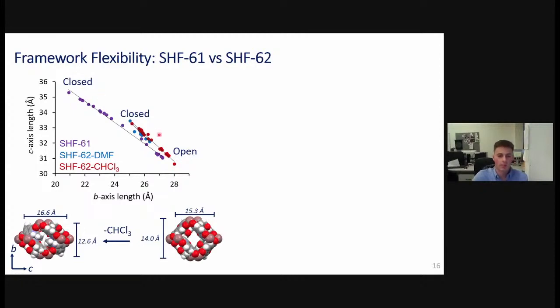If we plot the same single crystal diffraction data at various levels of desolvation for Sheff62, both from framework containing DMF in blue and chloroform in red, you quite quickly see that there's some key differences here. So the overall magnitude of this breathing behavior is significantly reduced. So it's about half when the framework contains chloroform, and about half again when the framework contains DMF. You also notice that the two starting points for the most fully solvated forms of the framework are quite different. So the framework containing chloroform is a much more open starting point than when the framework contains DMF.